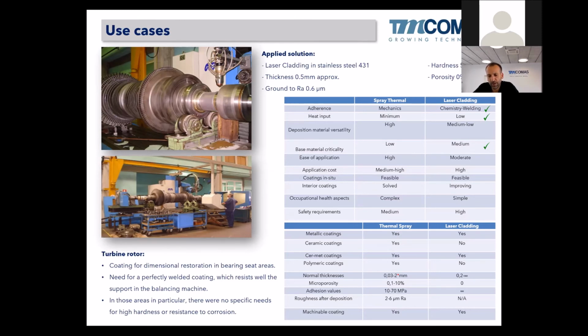if you repair the journal areas where the balancing machine should lean on by thermal spray, you have a very high risk of delamination of the coating. So the best solution is to weld. And if we speak about welding, the best option is laser cladding. So all the turbine rotors that we have repaired in COMAS, in journal areas, we are applying laser cladding to avoid delamination during low speed balancing.